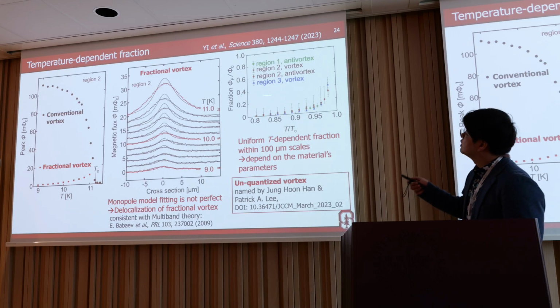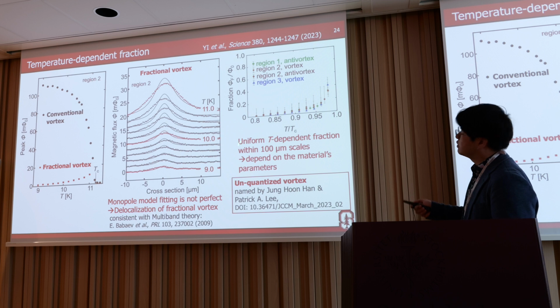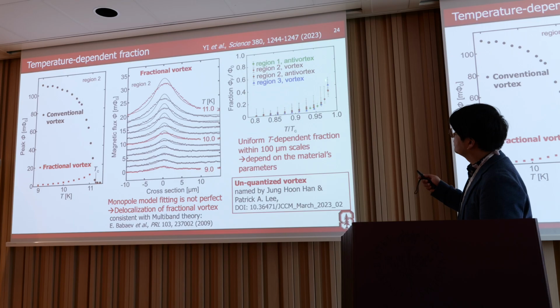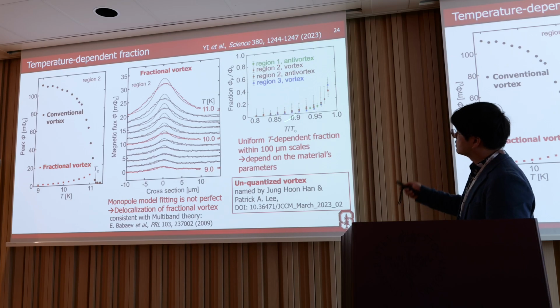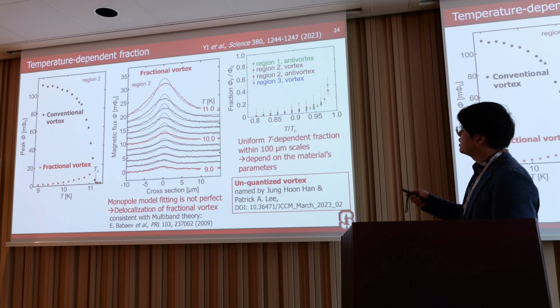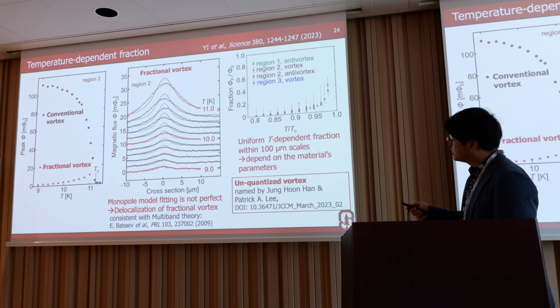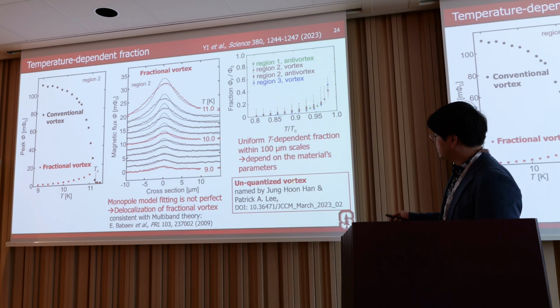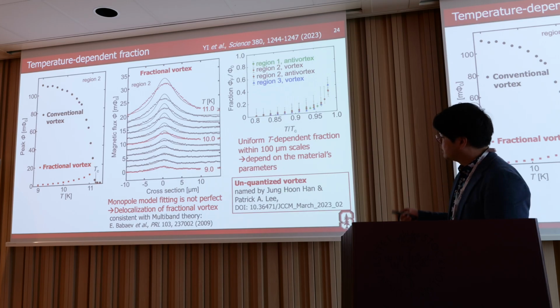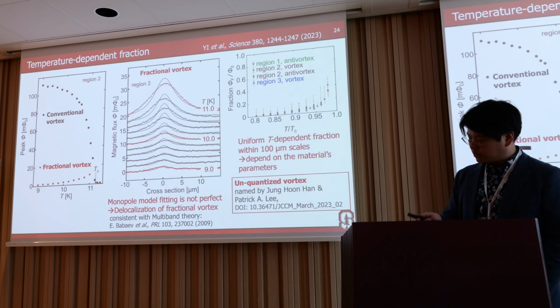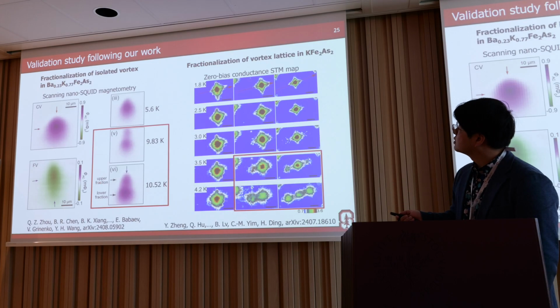Okay, so here I measured with a similar procedure at different locations over a 100 micron scale, and then estimated the fraction, and saw a very consistent temperature dependence. So this fraction number is temperature dependent, and I think it depends on the material parameters. And after publication, Jung Hoon and Patrick called this an un-quantized vortex, so we use this term for this vortex.